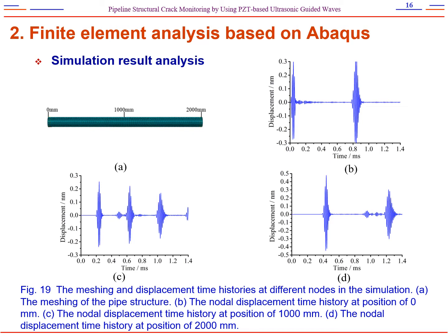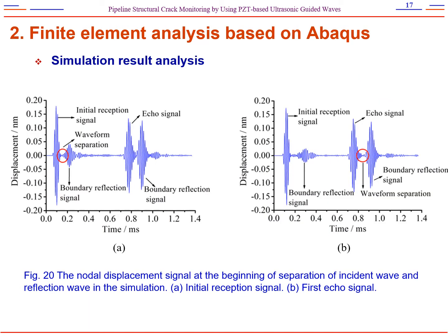Through the displacements compared at different nodes, it can be concluded that the incidence wave and boundary reflection ones will occur superposition phenomenon in the closed-end area. In order to determine the superposition area range, a new observation point of a signal wavelength away from the left end is selected. The node displacement of the initial sensing signal and its reflected signal starts clearly separating.